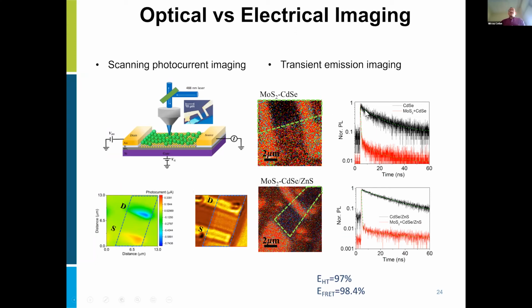Quantum dots on a non-interactive substrate show long lifetimes, which are indicative of no interaction. But once they're on this 2D material, we see the lifetime is completely quenched, for both hybrid devices based on core only and core shell, the first functioning on hole transfer, the second on energy transfer. If you compute the rates from these curves, you get quenching efficiency approaching 100%. So that tells us the process is highly efficient in both types of designs.